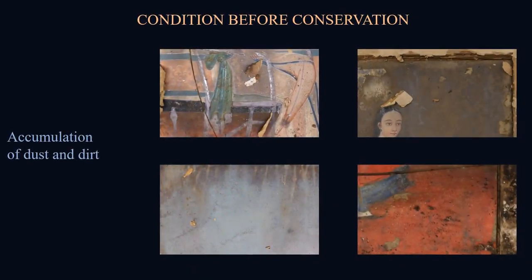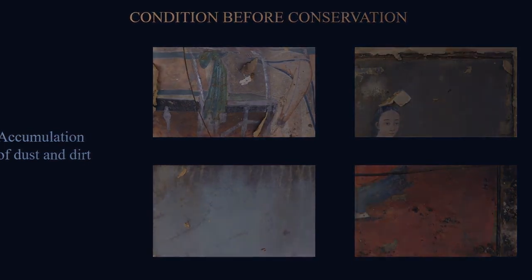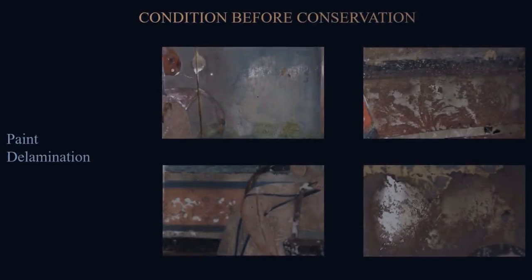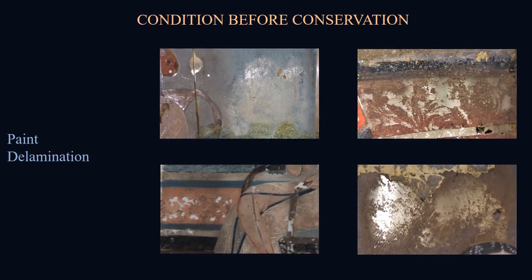I would like to discuss the condition of the object before conservation. There is accumulation of dust and dirt. Paint delamination which resulted in loss of paint. Such degradation of the paint layer is caused by internal or external factors such as composition of the priming coat and paint, drying mechanism, painting technique, or environmental instability.